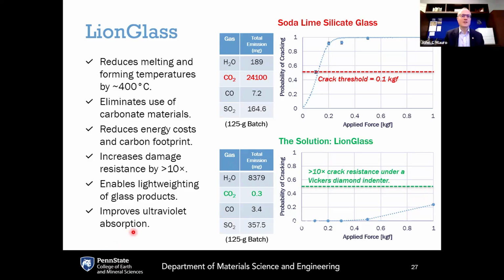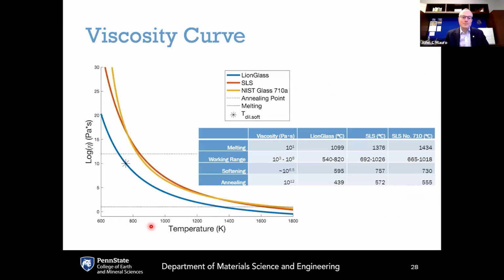One final advantage of Lion Glass is that it shifts the UV absorption edge a little bit towards the visible, so it actually improves ultraviolet absorption. So if you're using the glass for packaging anything that is sensitive to UV degradation, like cosmetics or some beverages, there can be some additional benefit there.